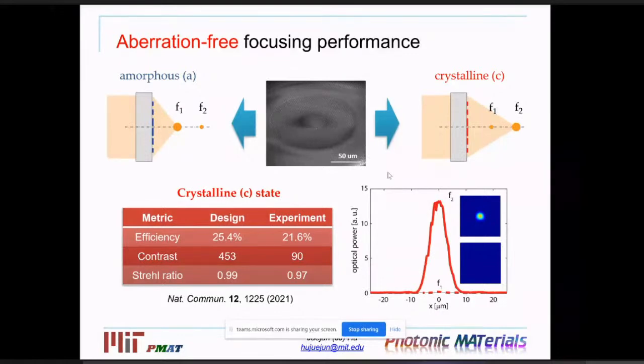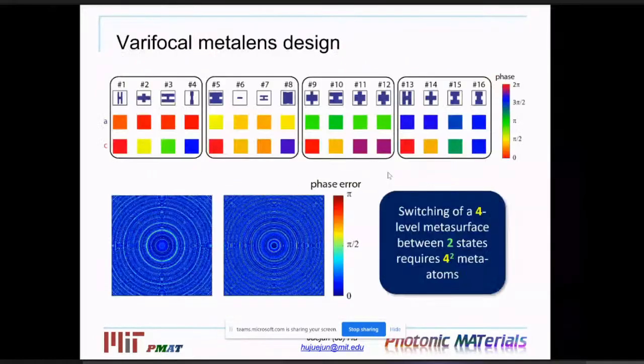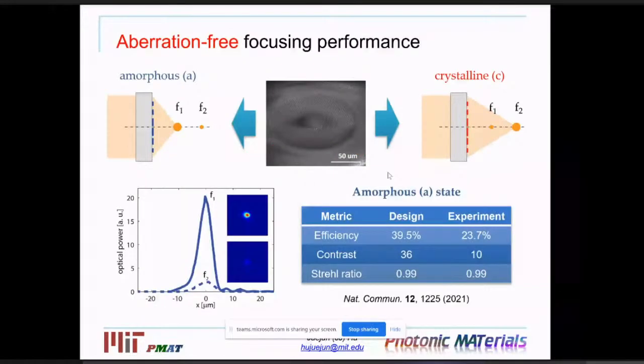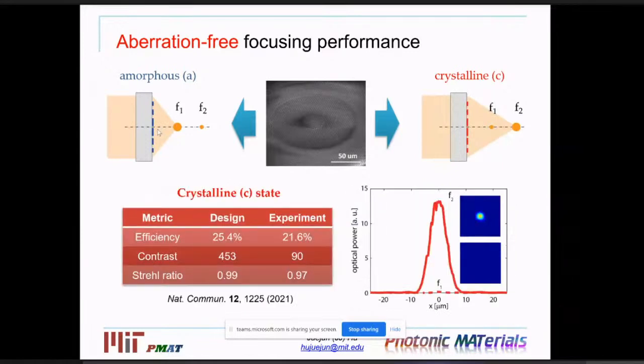In principle, we can realize arbitrary switching between any kind of different wavelength, because, like I said, we were able to cover a full 2-pi phase range in both structure states. So that means that we can switch between any kind of two different functionalities. Now, in practice, of course, this is limited by the numerical aperture of the lens, right? If you go to a very, very small focal length, then the NA, or numerical aperture, of the lens gets very large, and the focusing efficiency is going to get compromised. That's the main limitation. But otherwise, in principle, we can switch between arbitrary optical states, not just lenses, but between lens, gratings, polarization splitters, anything.